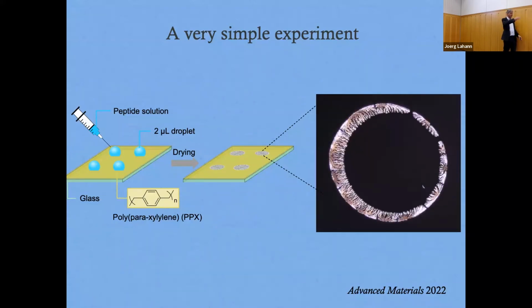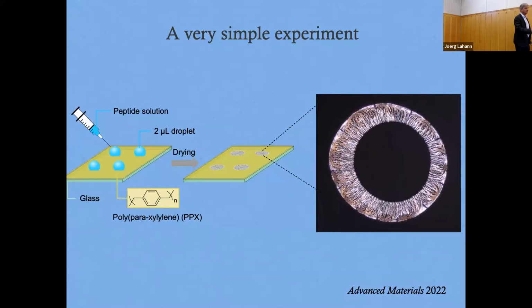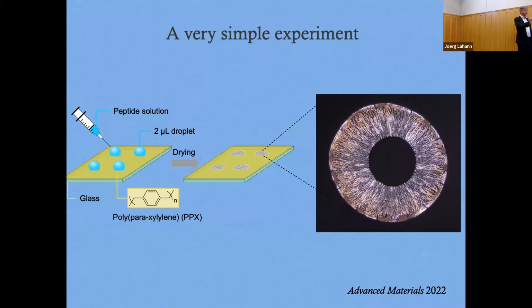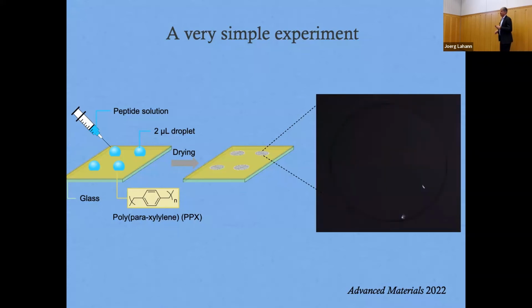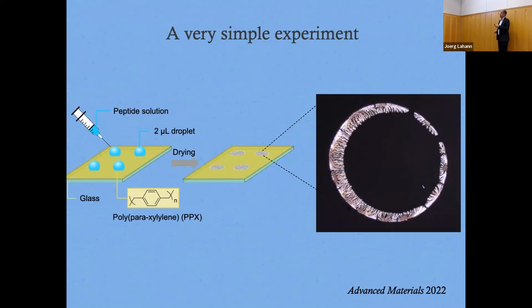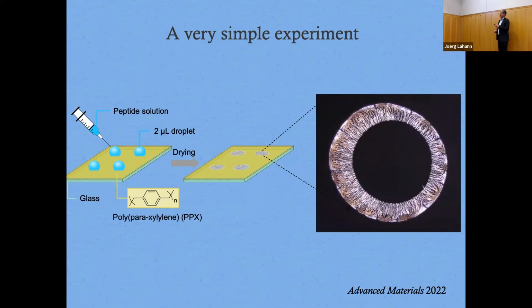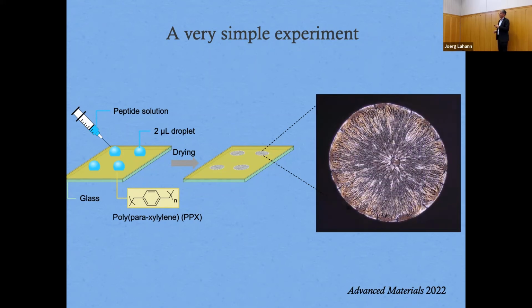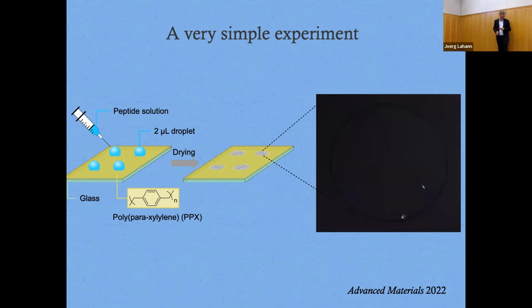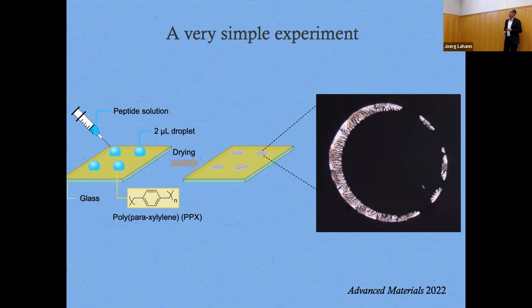If you take a needle and put a droplet on it, and that droplet is a protein solution with a little bit of salt, it's the most simple experiment that you can imagine. And we let it dry over time. What you see here is this accelerated video of what's happening with the drying. After this dries under defined conditions on a well-defined surface, you get very representative patterns, right? This mixture of protein and salt forms patterns.